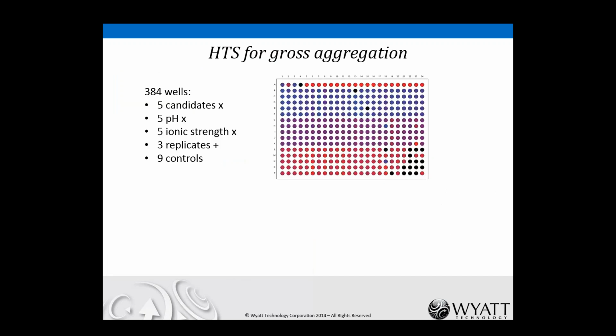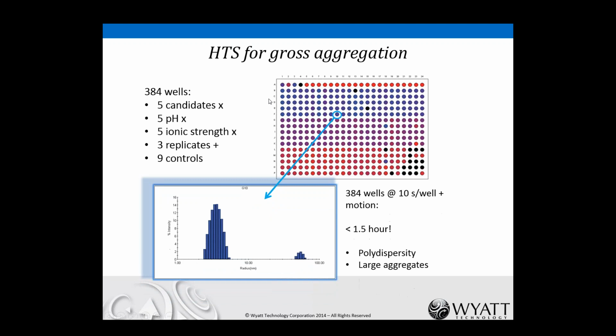So if you wanted to run a high-throughput screen just to assess gross aggregation, we could load up our workhorse 384-well plate with something like 5 different candidates, 5 different pH settings, 5 values of ionic strength, and do that in replicate as well as loading on some controls. It's always good to have controls for solid scientific results. And you can readily run through those with as little as 10 seconds per well, still get quite good data. And so that takes you about an hour and a half to run through the entire plate. And for each of those wells, you will determine the polydispersity, which is essentially the amount of small aggregates, as well as the presence of the large aggregates, which we see over here at about 80 nanometer radius.